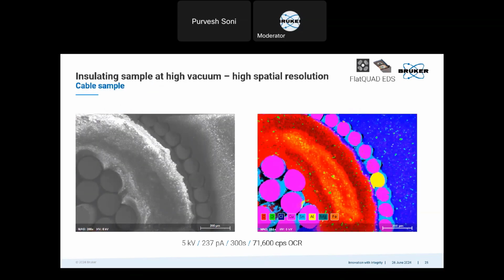And this is an insulating sample measured at high vacuum to get high spatial resolution. So this is a cable sample, and we know that cables have very heavily insulating layers. And we can see how nicely we could map with the FlatQuAD because of the high sensitivity. And even at such low probe currents, I could get an output count rate of 71,000 counts per second.